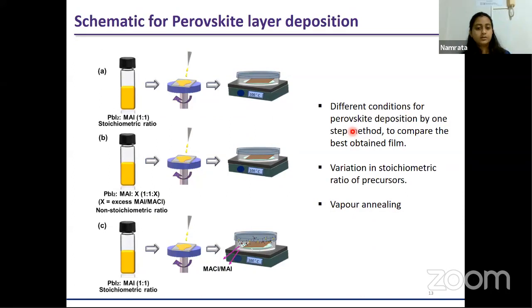Here is a schematic showing the steps we incorporated for the perovskite film deposition. We chose three conditions for the perovskite film preparation. We used a stoichiometric ratio of precursors as in figure A, 1:1 PbI2 to MAI. Second, we changed the stoichiometry and increased the amount of the methyl ammonium halide. In figure C, we again used the stoichiometric ratio, but compared to figures A and B, where the annealing is directly in its own atmosphere at 100 degrees Celsius, we used a vapor atmosphere of methyl ammonium chloride and methyl ammonium iodide.